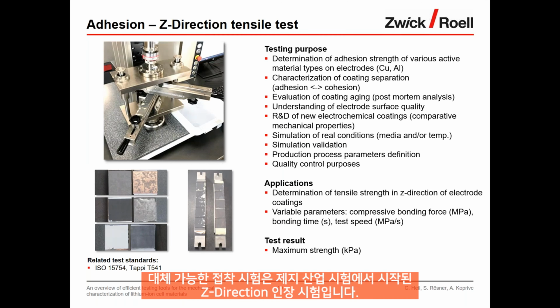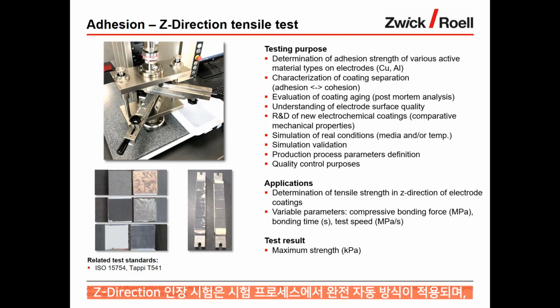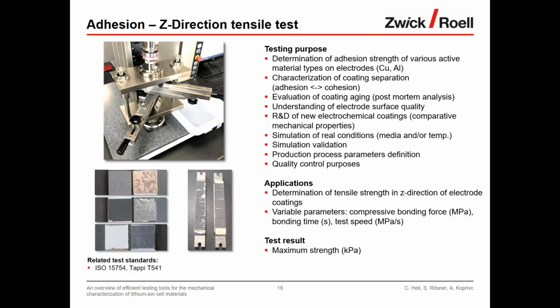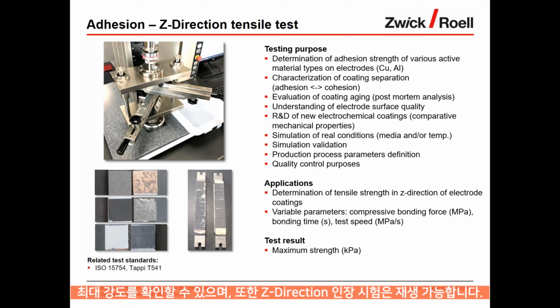An alternative adhesion test is the Z-direction tensile test, which was derived from a test in the paper industry. Here, the testing process is fully automatic, and the machine eliminates the flaws of the peel test. This test fixture allows you to program the relevant parameters, especially the bonding pressure, the bonding time, as well as the test speed, and thus reduces operator influence quite significantly. The result is a clear single data point. So we're looking at maximum strength, and this test is well reproducible.